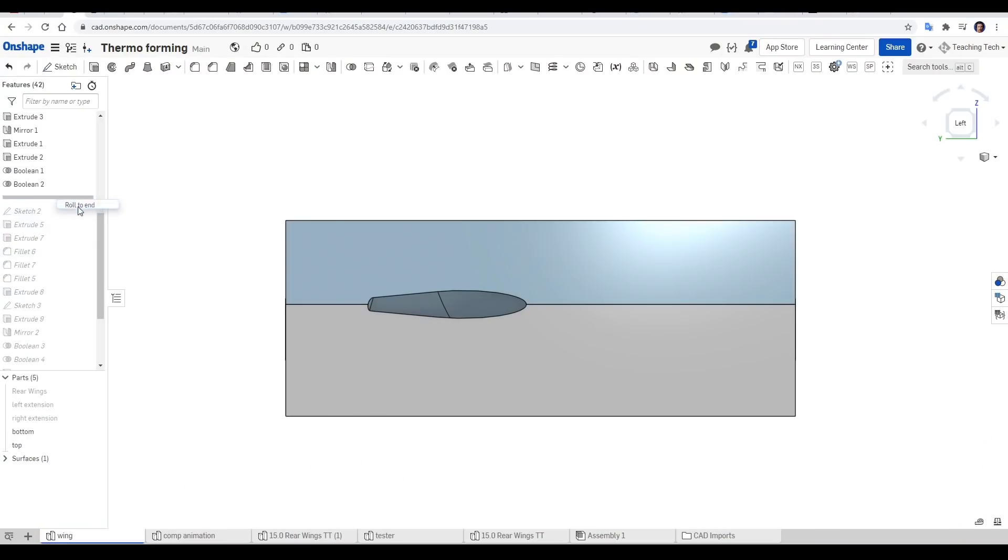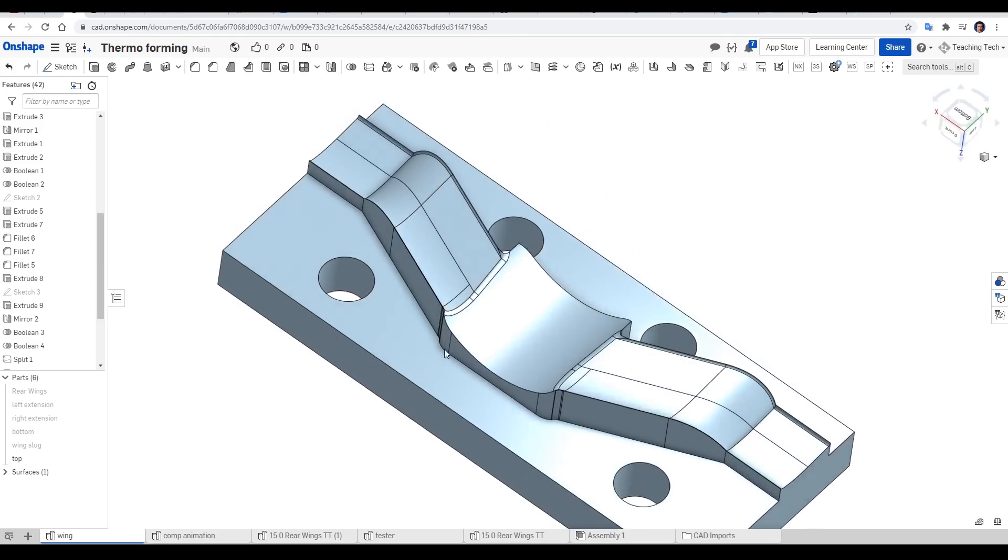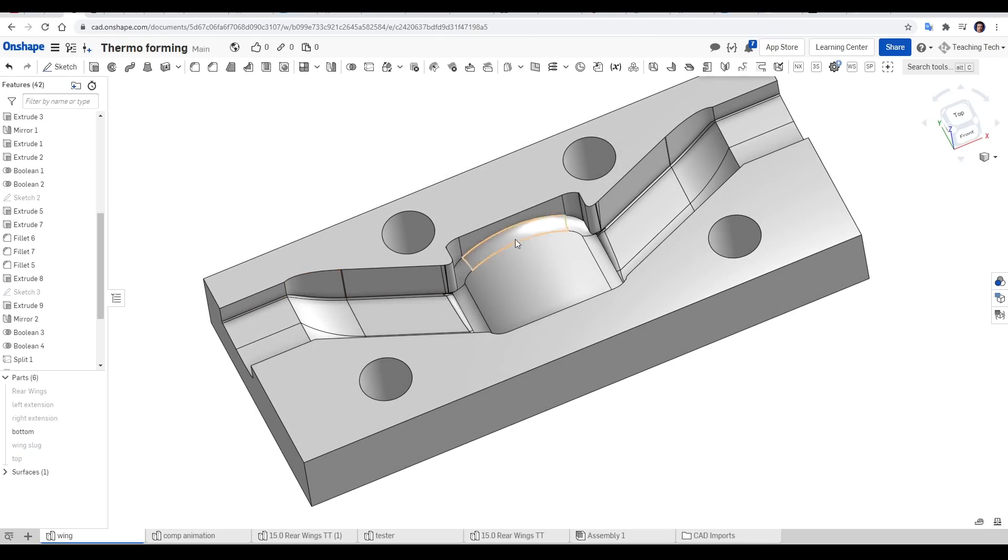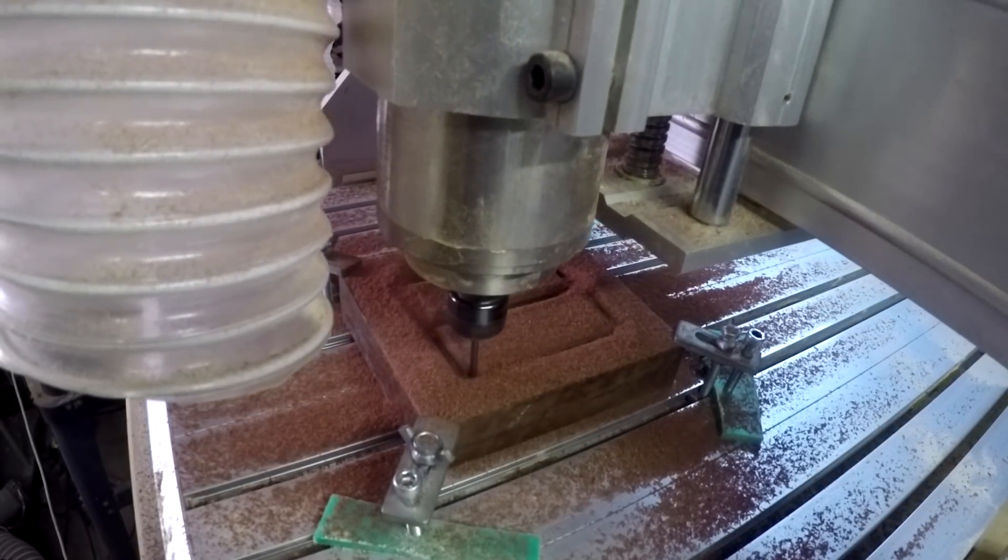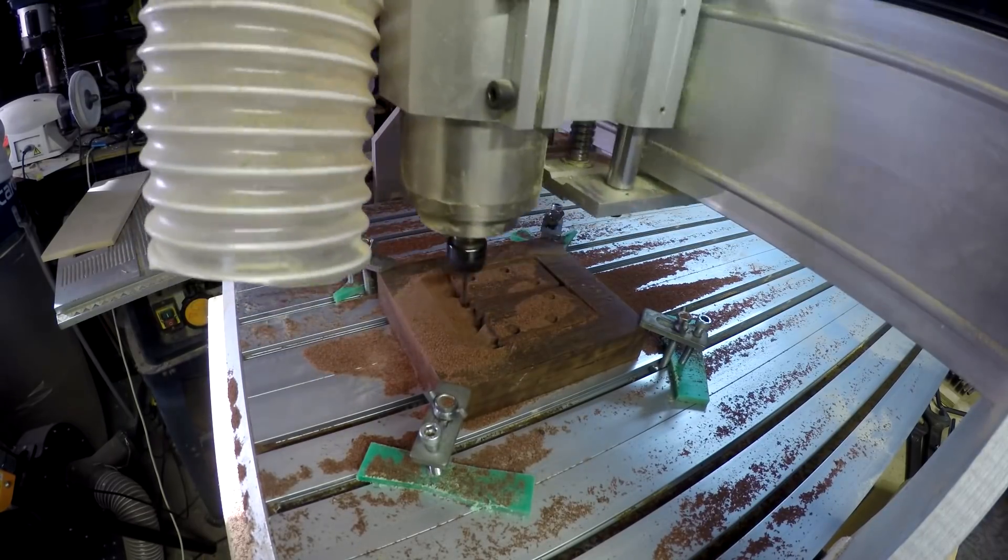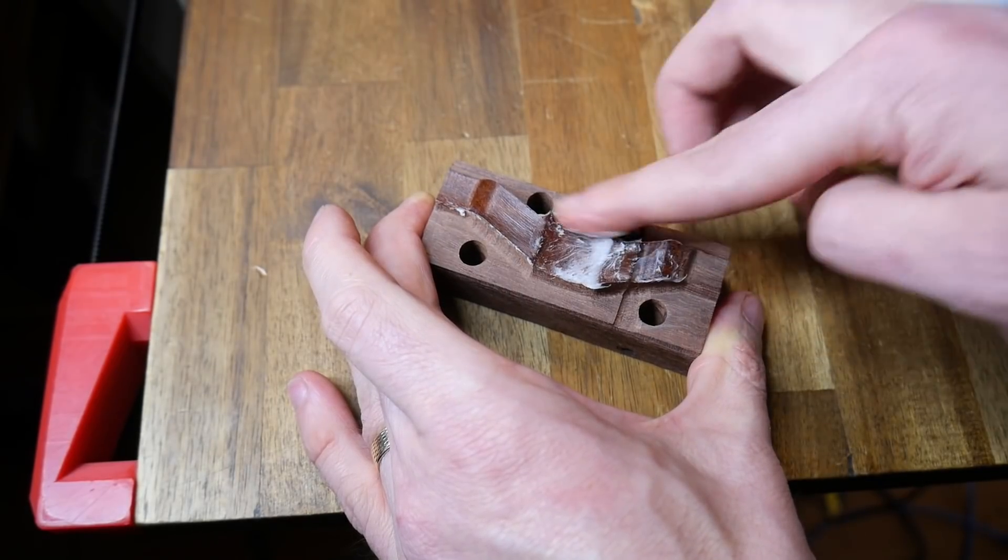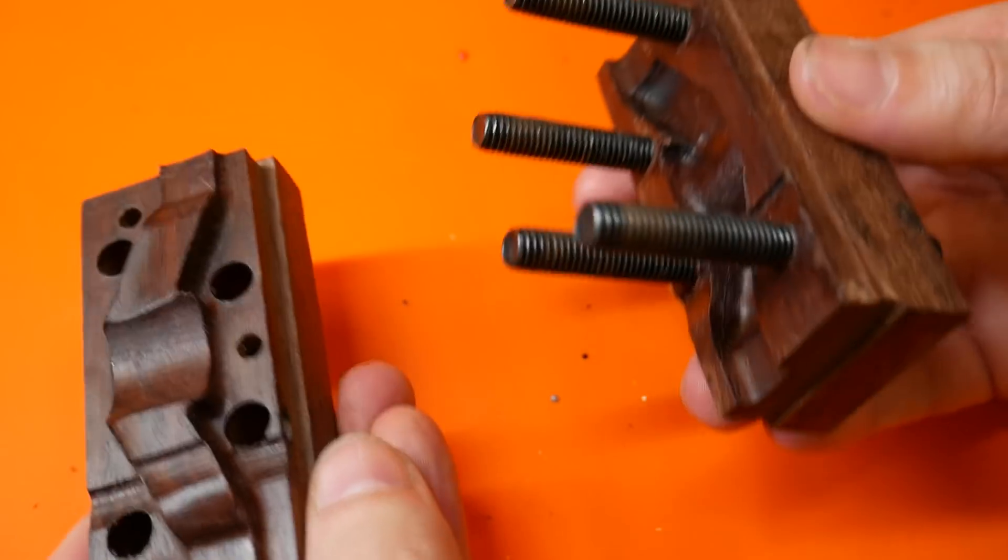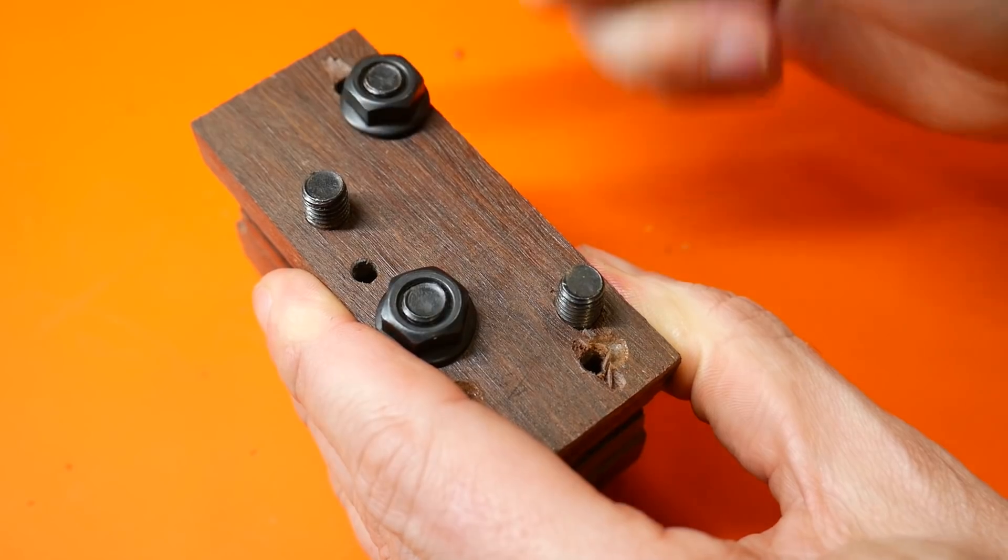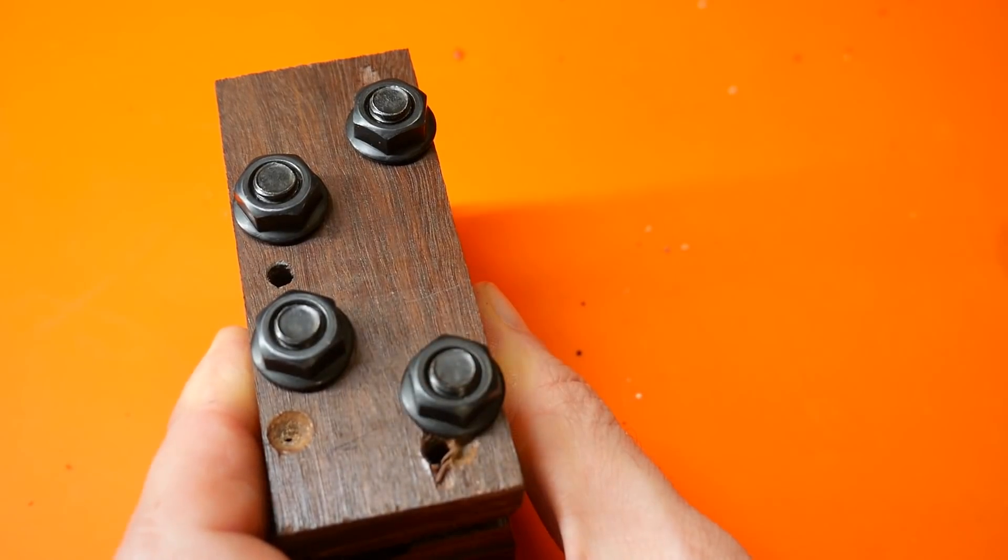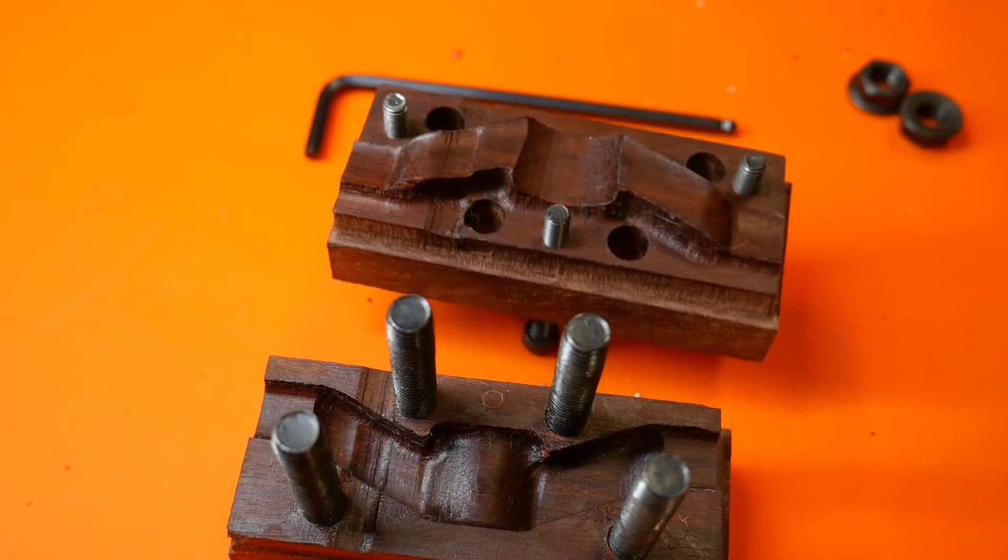The other weak point here is the design of the mold, so I modified it to offset where the two halves met. You can see that on one side the internal cavity is shifted upwards, whereas on the other half it's quite recessed. This drastically reduces the risk of the plastic oozing between the two halves and creating flashing, and it's a lot closer to the animated example I showed you earlier. I machined the mold pieces with the same technique but this time chose a really dense hardwood. This would give a less fluffy, more precise edge, and it didn't take too much longer to machine. This time around I applied the wax straight away, and compared to oil it doesn't swell the surface as much. The other thing you'll notice is a big improvement in the way the two halves mate together, thanks to some threaded holes and some long M8 bolts. Now the nuts can be tightened on the other side to pull everything together evenly. In one half I also threaded some holes to drive in some bolts to release the two halves of the mold.